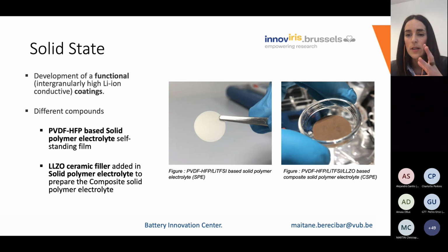This is a little bit of pictures of what we are developing in the lab. So we are working with the PVDF-based solid polymer electrolytes so that they can be self-standing, and with ceramic fillers like LLZO to be added to the solid polymer electrolyte, and at the end prepare this composite solid polymer electrolyte. At the end, we need to test everything together so that we can create a battery.